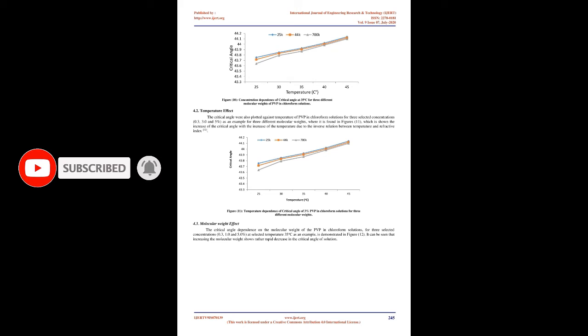It indicates that at the fixed concentration, the refractive index decreases linearly with the temperatures 25 to 45°C. This is because the increase of the temperature leads to a decrease in the particles of solution in the volume unit and decreases the density of the solution 26, 28.